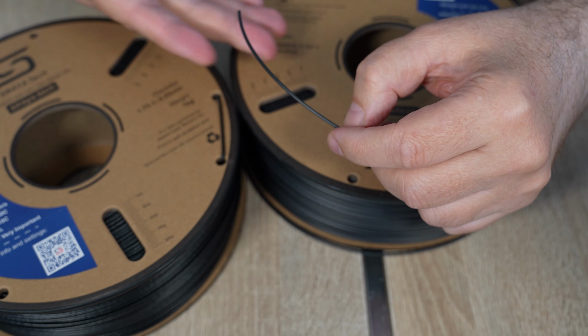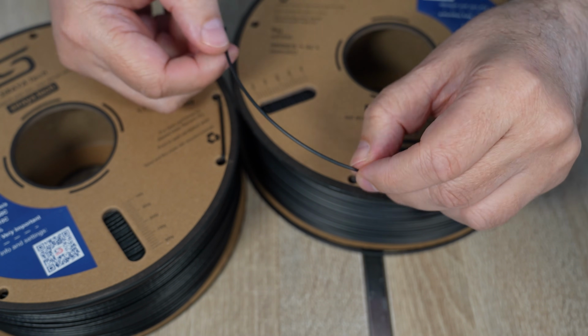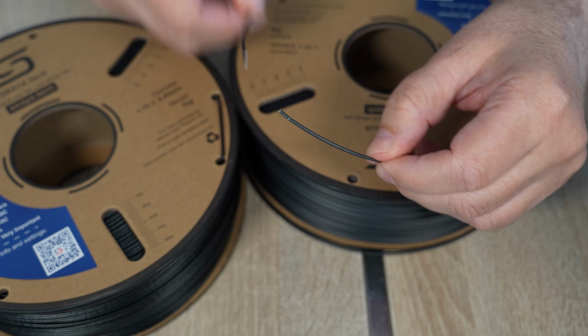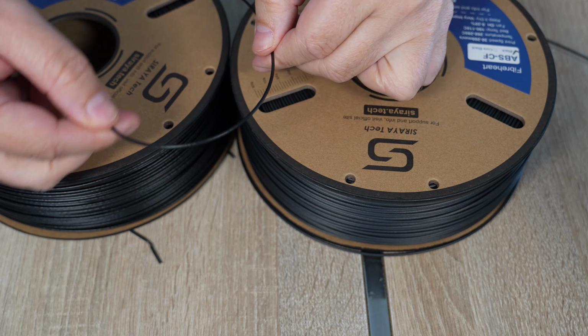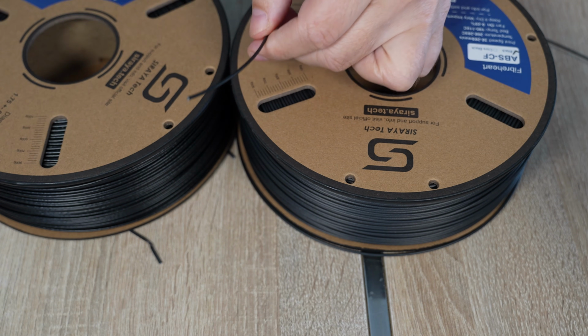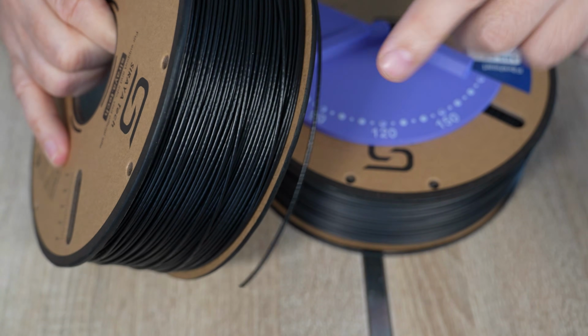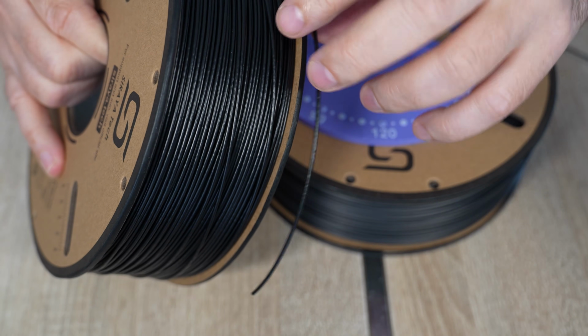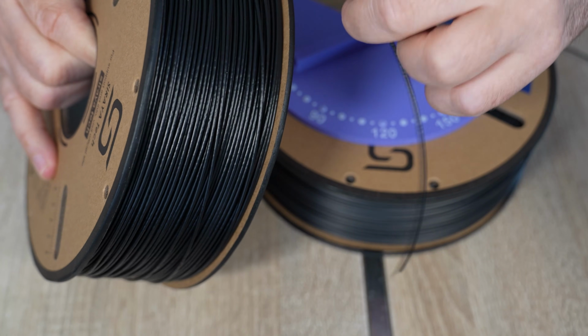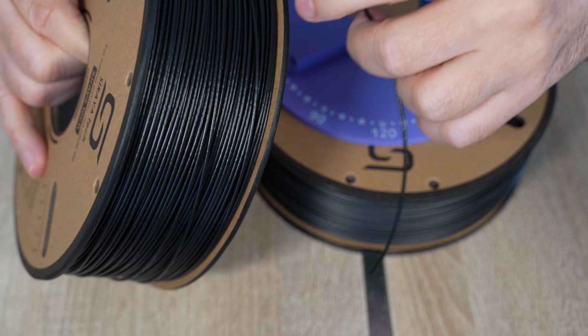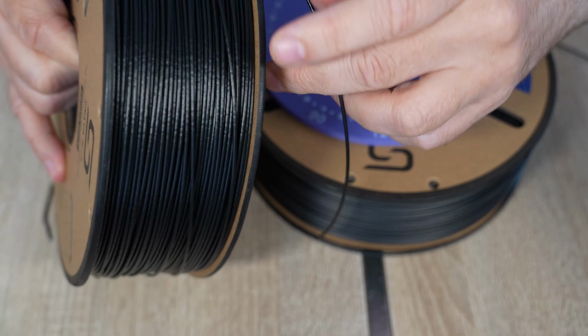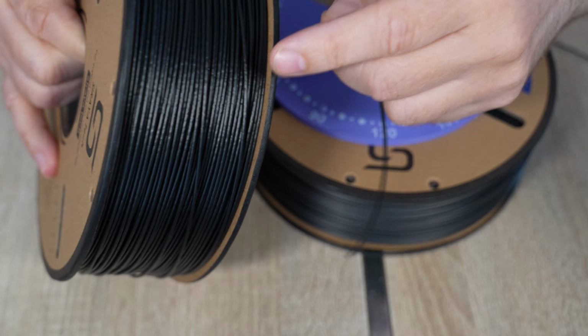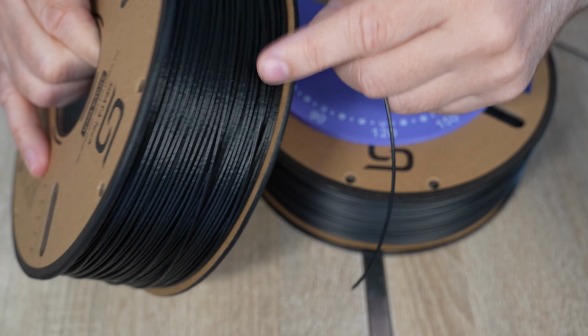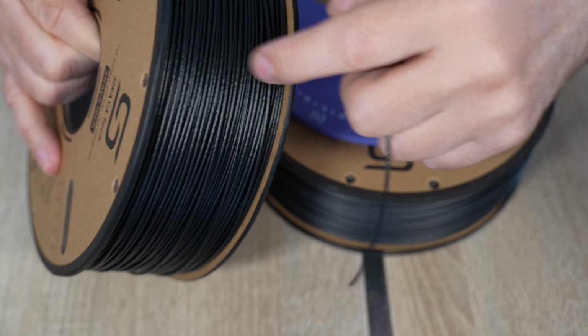Let's see how brittle the filament itself is. This is the regular carbon fiber version. And this is the core version. Let's measure it. Before the measuring, I want to mention this. Because of the smaller density, they have to place more filament on the spool to have that 1 kilogram. But in this case, I would prefer either a bigger spool, or let's say having 0.9 kilograms on the spool. This may fall down during the printing.